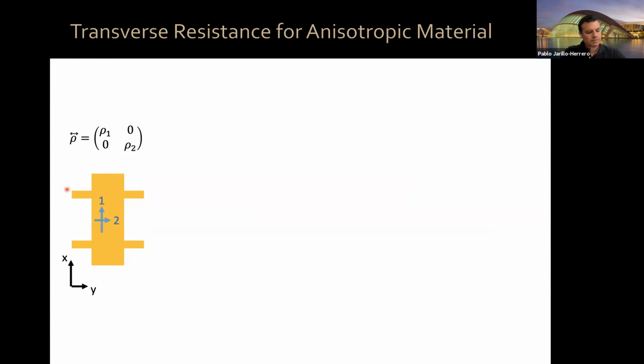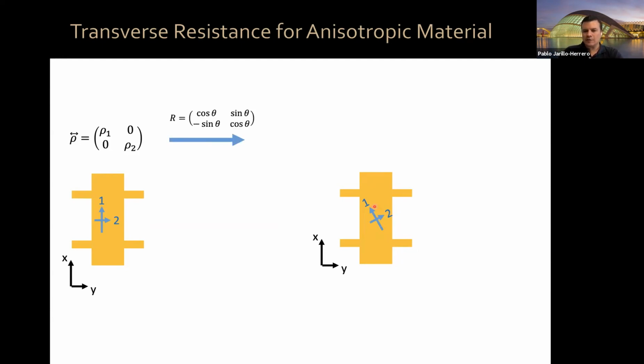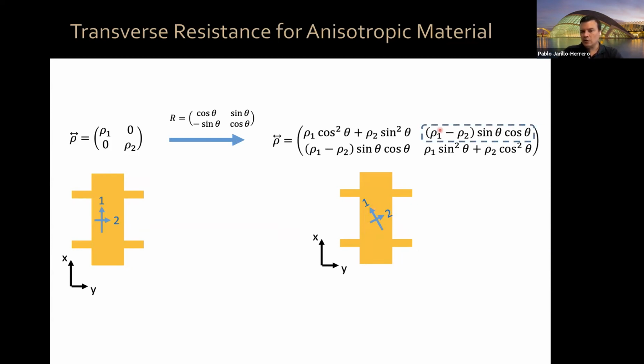Now, the thing is, when we fabricate a device in general, we don't know if our anisotropy axes are oriented in the same direction as the device that we etch, okay? Because we do not have information about the crystallographic orientation of our magic angle bilayer graphene, okay? So if you take the most generic case where you have an anisotropic material and now you make a Hall bar on it, the Hall bar axis will not be aligned with your anisotropy axis. And then you have to do a rotation transformation of your resistivity tensor. And in general, if you have anisotropy, if rho 1 is different from rho 2, okay, then you expect to have an RXY component in your system. Okay? So as long as the sine of 2 theta is not 0, you expect to have a rho XY which is proportional to your anisotropy, to the resistance difference.